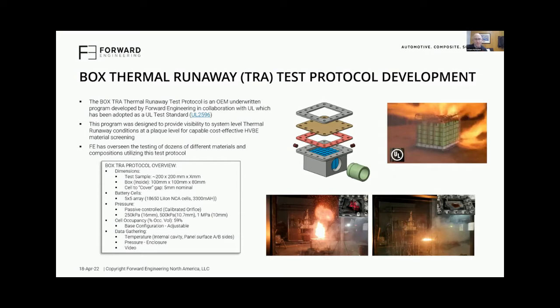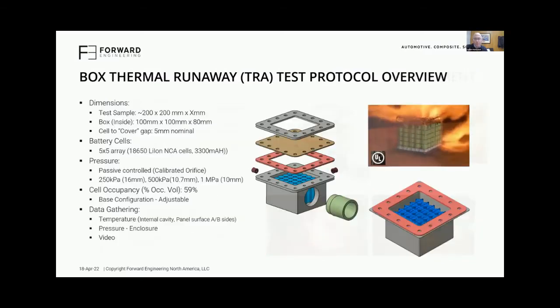So what that test is, and I'm going through rather quickly, I apologize, with the limited time available, I want to share as much as we can about this exciting development. UL 2596 was actually published in January, but essentially, what we're doing is utilizing a 5x5 array of lithium ion cells, 18650 cells, and we're initiating thermal runaway of those cells and imparting that energy on the sample. So when you look at the image on your screen and you see that brown panel, that is the sample under test, typically around 200 by 200 millimeters by an appropriate thickness. The nominal thickness is typically around 2 millimeters.